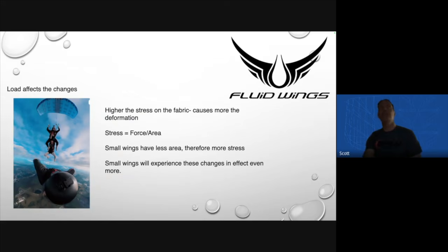What affects these changes? What's the primary driver on it? Well, yes. Loading, yeah. So the higher loaded, the higher the deformation changes. Now, this is an important thing. It's stress that does this, guys. So it's not just that your 60 square foot HK2 shows it more. It does. So a millimeter of deflection on a HK260 will be way more evident than a millimeter of deflection on a Prime 280.